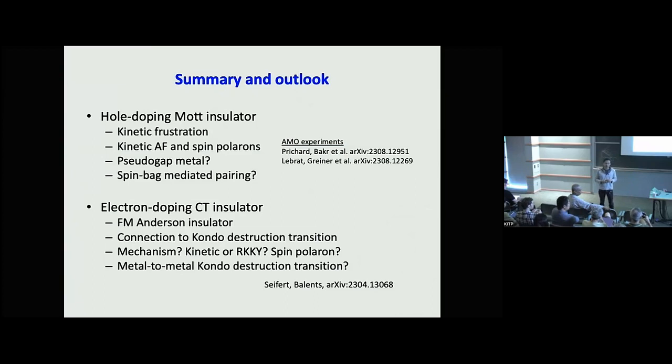But the momentum has to go somewhere, doesn't it? Yes. Then I think you're really interested in the question of a multi-electron-hole process, if you have itinerant carriers. You have a population imbalance for the itinerant carriers. That's harder, right? Then you need a polarized atomic-scale defect to mediate, maybe it happens at the boundary or something. No, but we must have this kind of atomic defects in the system. That density is about 10 to the 11 per centimeter squared. Moiré density is 5 times 10 to the 12. You can convert, it's 2 to 3% of the Moiré density, right? So it's not insignificant. It's not that low. Yeah.